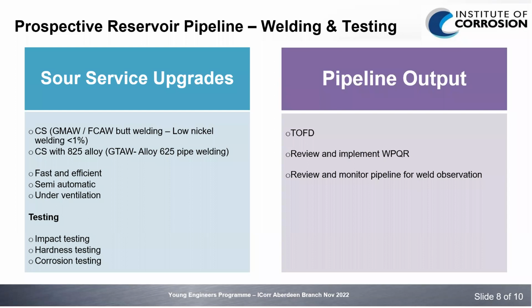We do the testing. On the impact testing, there needs to be 6 millimeters wall thickness. Hardness testing, on the Vickers hardness test on the weld. Corrosion testing, minimum 24 hours, 40 degrees. And then we do the TOFD, time of flight diffraction, to have a good survey in place and a good corrosion management in place. Then we review and implement the WPQR certification, so we could track and trace on the weld, and then review and monitor the pipeline on well observation.